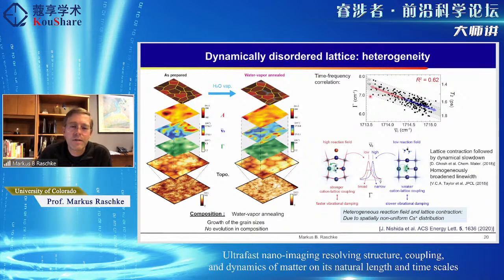And so what we'll see primarily in a nutshell here, the result is that we actually see a correlation between a spectral narrowing and a blue shift, or inverse, we see a red shift in spectral broadening of this vibrational resonance. And these types of correlation then tells you actually a little bit what the microscopic process is. And this is that when you have, for example, a heterogeneous cesium ion distribution that gives rise to a distortion of this lattice, which then gives actually rise to stronger cation lattice coupling and faster vibrational relaxation. Whereas if the lattice is less perturbed, and instead of the cesium cation, you just have the organic cation, then we have a weaker cation lattice coupling and the slower vibrational damping.